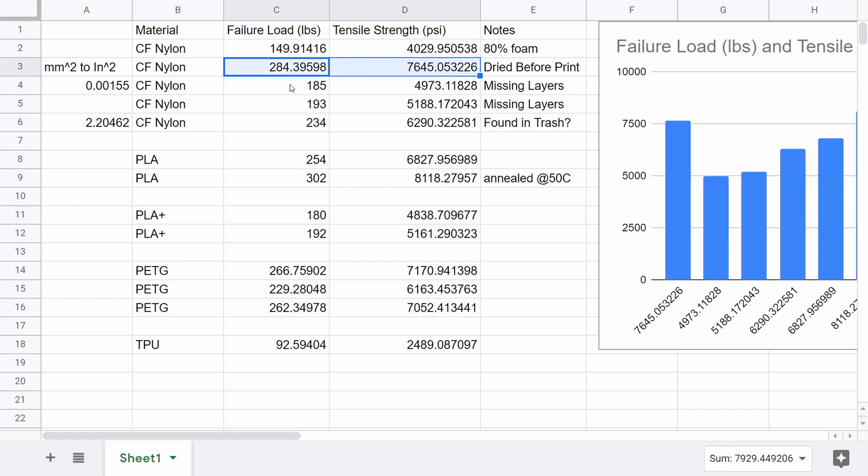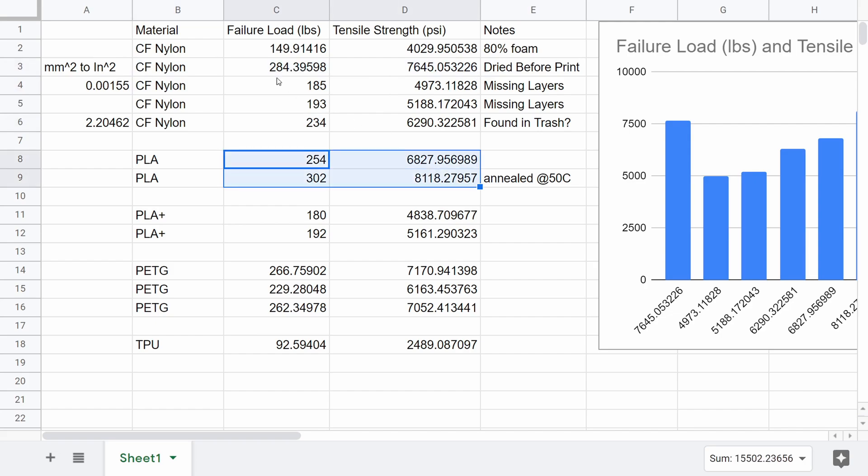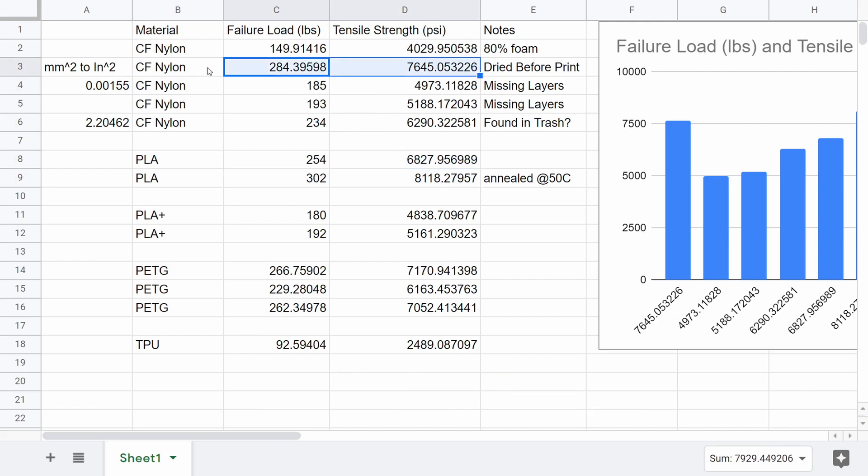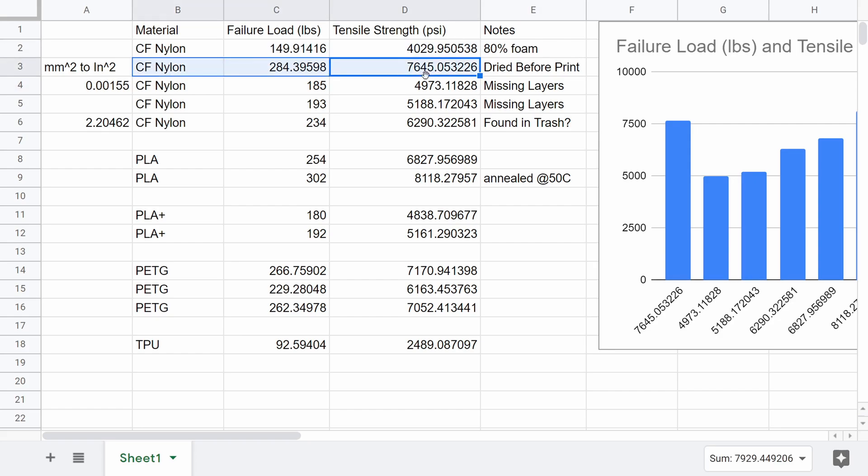Overall, I was expecting the carbon fiber nylon to do a little bit better than it did. I want to repeat this test and anneal some of the carbon fiber nylon and not lose the samples, but that'll have to wait for another video. Another advantage that carbon fiber nylon has over PLA is that it has a higher softening temperature. If you're making something that's going to be exposed to elevated temperatures, say it's something that'll be baking in the sun in a hot car, or if you're making some kind of electrical device that gets hot, like a motor, then the carbon fiber nylon would still be a material that you'd want to use.